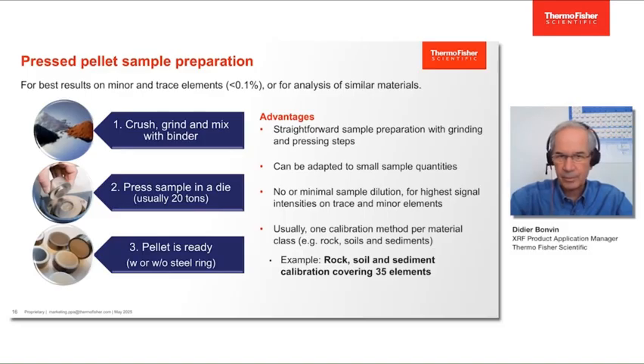So this straightforward sample preparation with grinding and pressing steps can also be adapted to small quantities if we don't have enough material. There is no or minimal sample dilution. Maybe the dilution is brought by the binder, but generally we will never use more than 10% binder, in the cases the powder does not agglomerate well, which means we get the highest signal intensities on the trace and the minor elements. The drawback is that the calibration generally can only be done for one type of sample